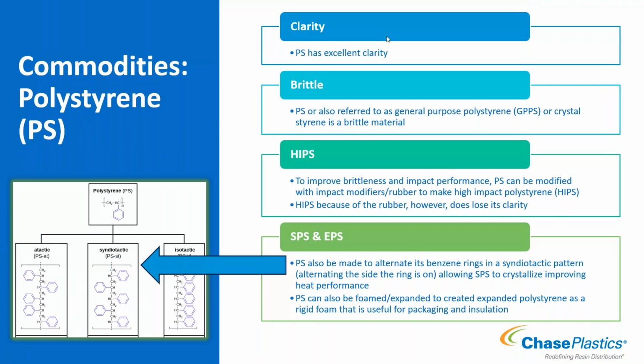But what we can do then is we can add stuff to it to improve that brittleness or that impact performance. So high impact polystyrene, HIPS, we will take a rubber or impact modifier and add it to the polystyrene. It improves its impact, so you get a better impact performing product at that time. Because of the rubber though, it does affect the clarity. So standard GPPS is clear, very good clarity. As soon as you add something to it, like the rubber for HIPS, it's no longer a clear product. So you do lose that.